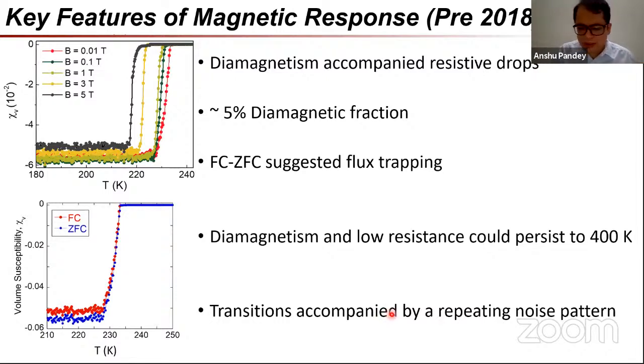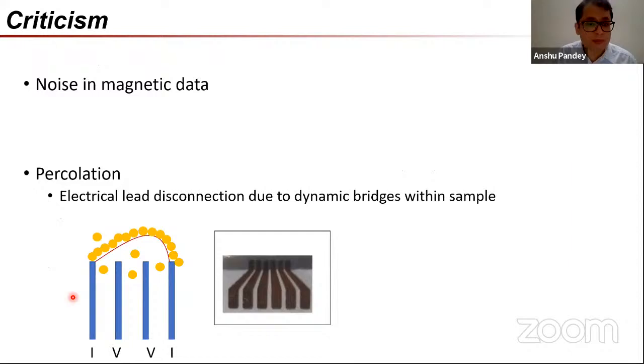Ultimately, however, there was a problem with everything which we did, which was that in the state which is the diamagnetic zero resistance state, the magnetic data seems to be accompanied by a repeating noise pattern. And when this was pointed out, we didn't really know of its existence, but then when we found out, we also located that this noise pattern is quite ubiquitous. It was even there in our FC and ZFC data, which we had not even bothered making public at that time. So the criticism which our work faces is twofold. One is the noise in the magnetic data, and the other is percolation.